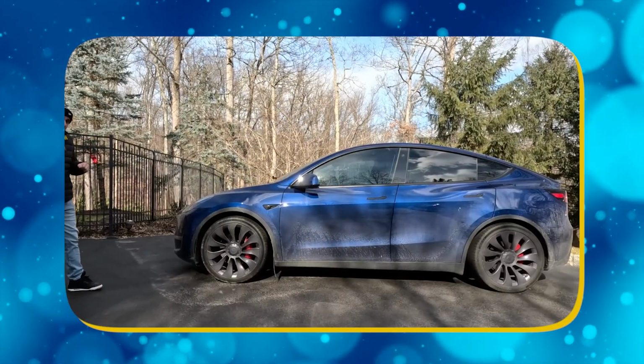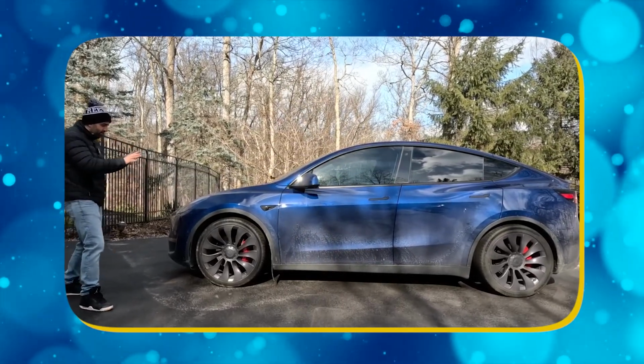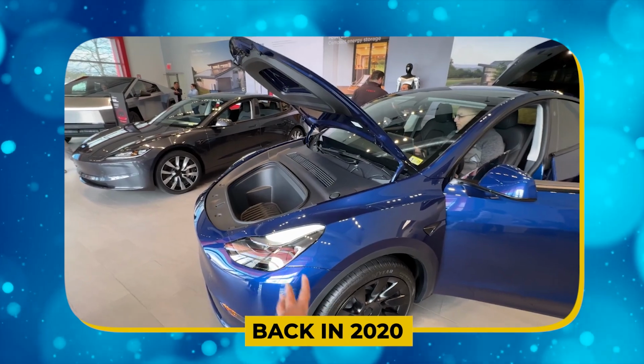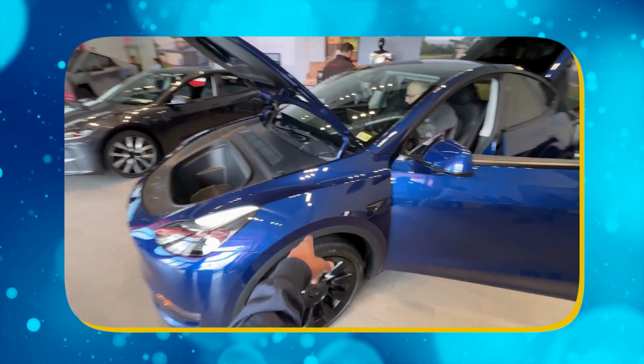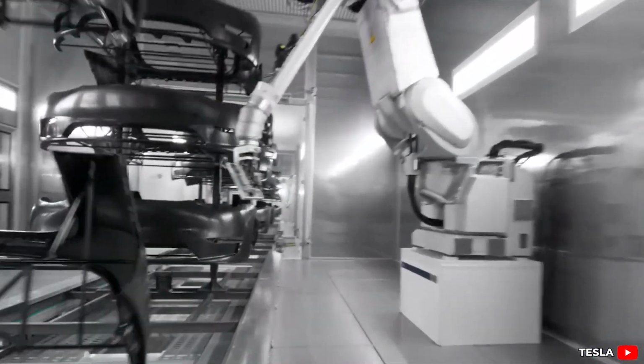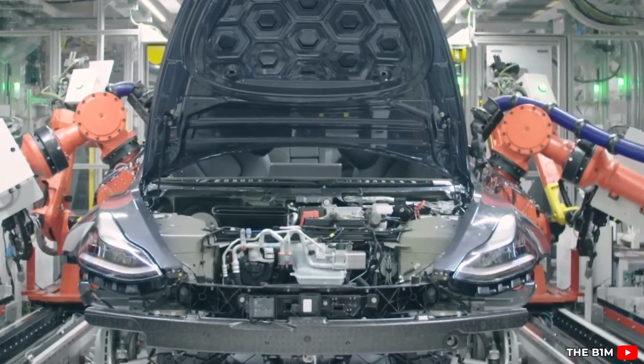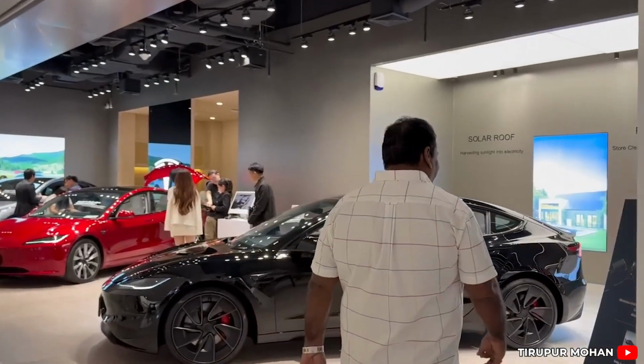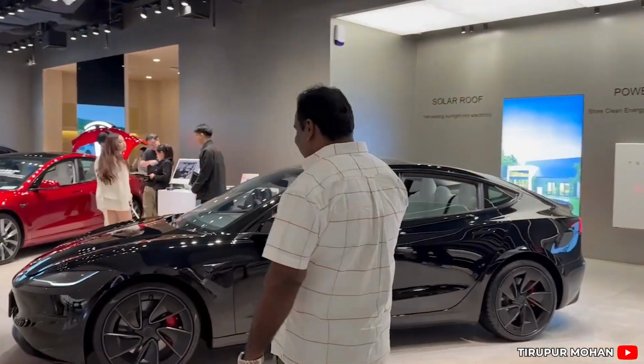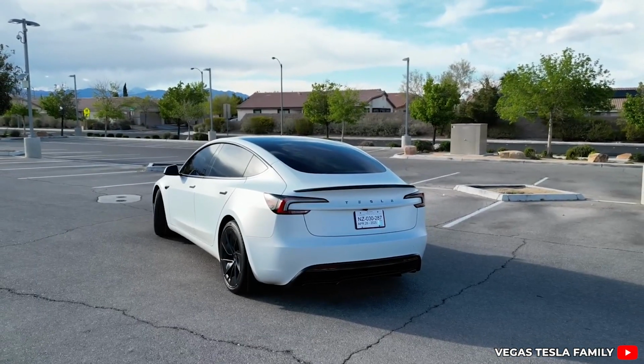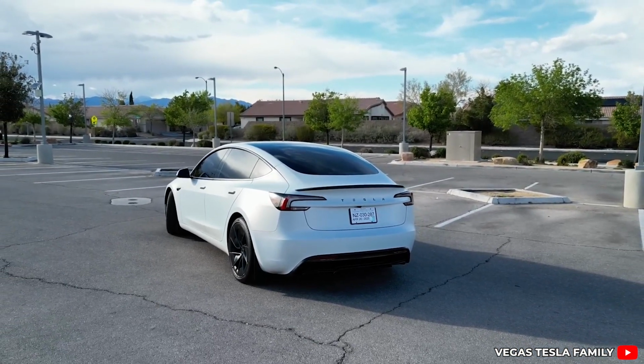That's how they were able to cut casting cycle times drastically. Back in 2020, it took around 170 seconds to complete one cycle using the 6,000-ton press. Now, it's down to 75 seconds. That's less time than it takes to microwave a frozen burrito. These faster cycles mean more cars, more parts, and more consistency.